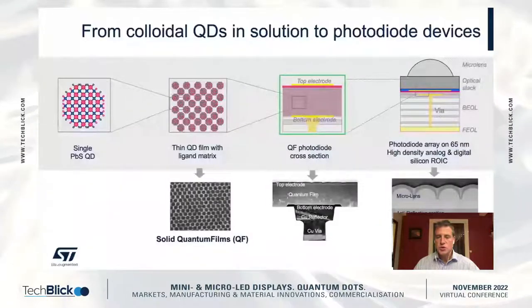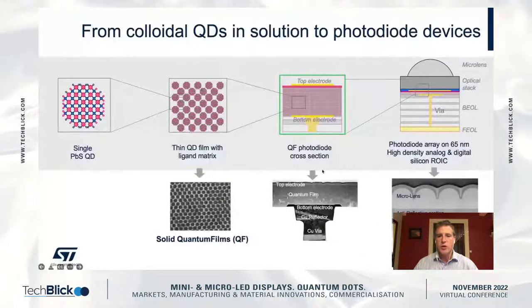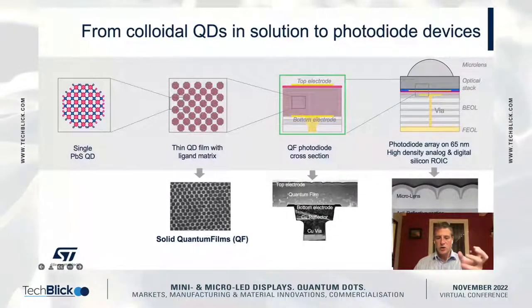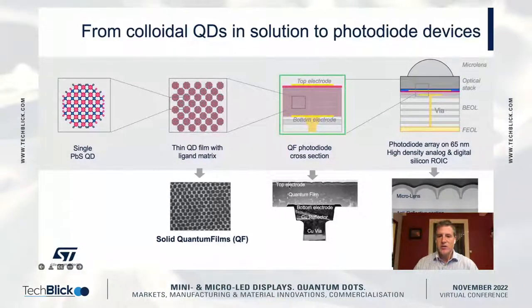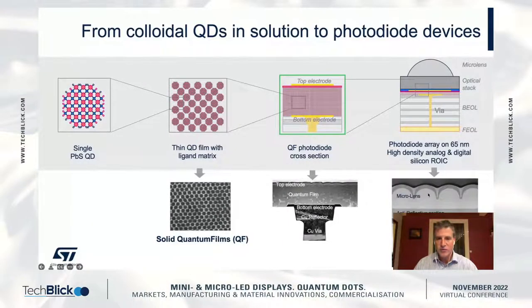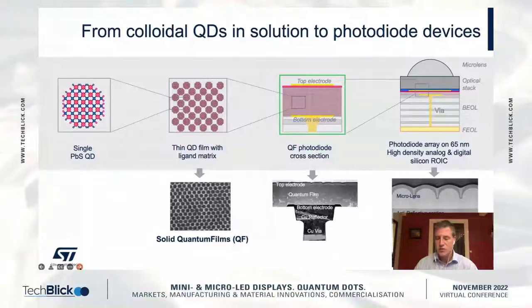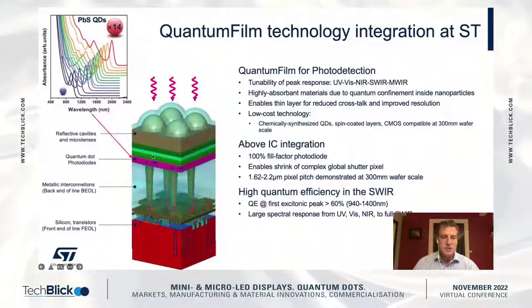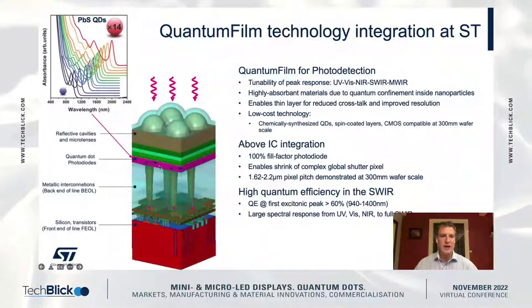We spin coat on 300 millimeter wafers and use the copper electrodes that provide the structure of the pixel shape and size. We then complete the rest of the device with the electron and hole transport layers, the QD film, encapsulation, and microlens array. Basically, that gives us a full encapsulated structure where the quantum dot film is the active layer absorbing photons and creating electron-hole pairs.